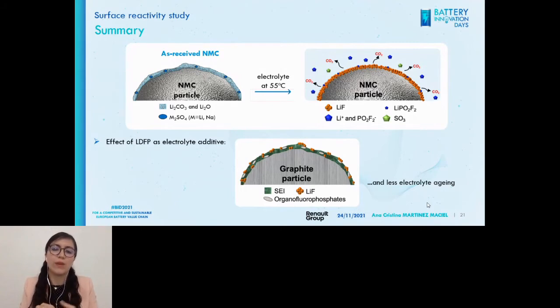The effect of LiPO2F2, as we saw as electrolyte additive, was mainly on the negative electrode because it enriches the SEI with LiF and organofluorophosphates. And of course, this will lead to less electrolyte aging.